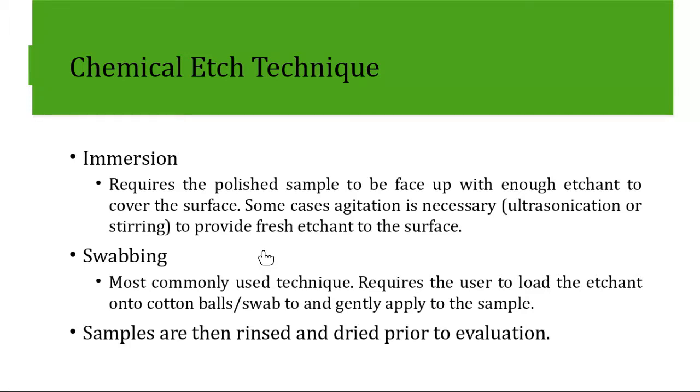attack across. In both cases, once the samples are satisfactory, you'll rinse them, hot water, warm water. You'll have to dry them before you evaluate. So when you rinse the sample, not only will you rinse it with water, but then you'll want to rinse it with enough ethanol, or you can even ultrasonicate it to make sure that you do not have water on the sample. So when you dry it, you stain the sample less, making your evaluation less painful in case you don't like stains on your sample.